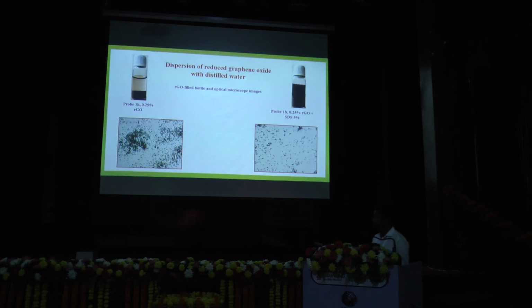These are the images of dispersion of reduced graphene oxide. This is the probe sonicator, 1 hour, 0.25% RGO. This is the probe sonicator, 1 hour, with 0.25% RGO plus sodium dodecyl sulfate. Without sodium dodecyl sulfate, this is the image of without using it.